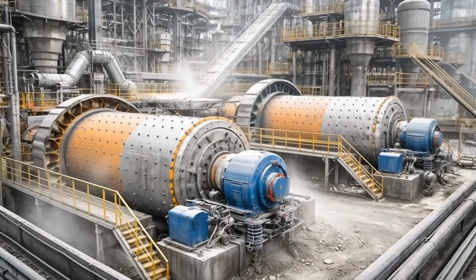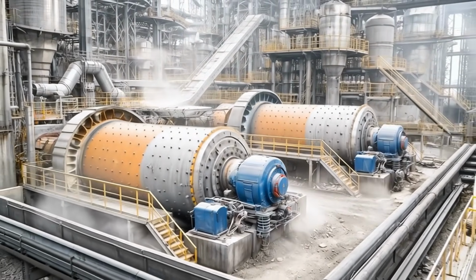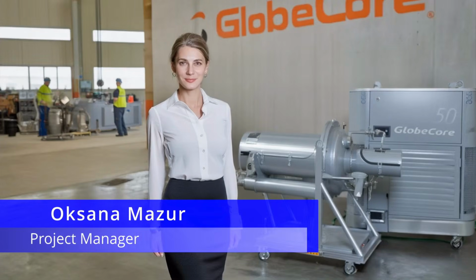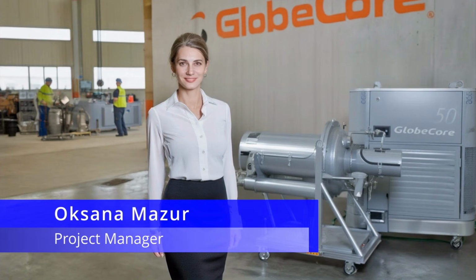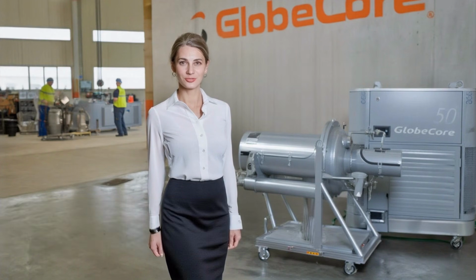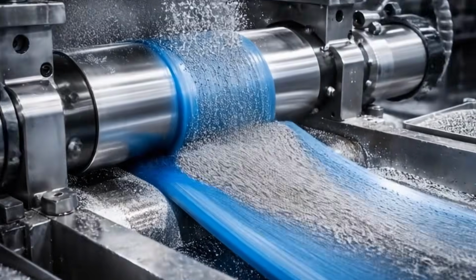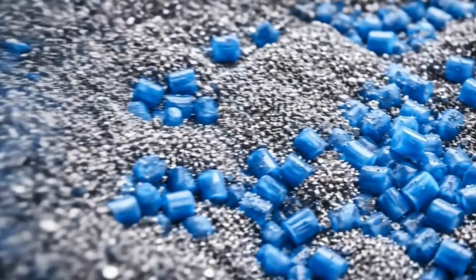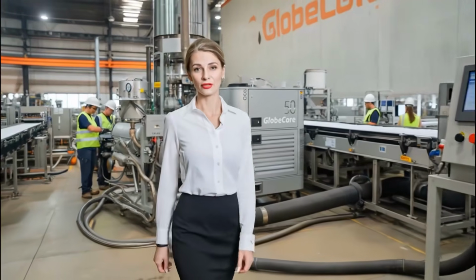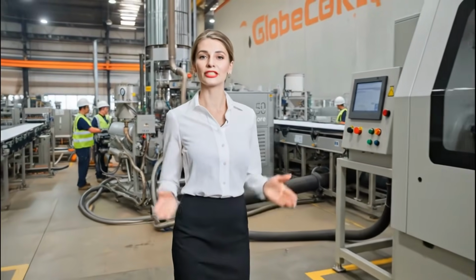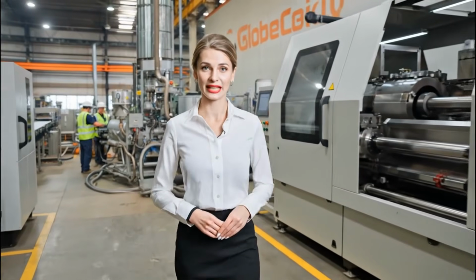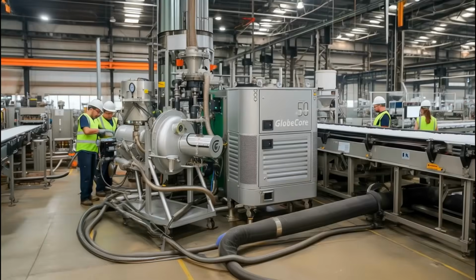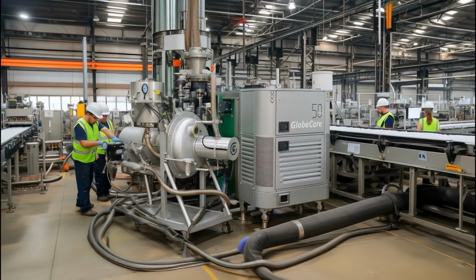That is why processing in AVSp produces an effect unattainable by conventional mechanical mills. In conventional mills, similar processes take tens of minutes or even hours. In AVSp, it takes just tens of seconds or even seconds. But the key difference is not just in speed. A ball mill forms a mechanical mixture where the components remain as separate phases. AVSp creates conditions in which the metal is fixed on the surface of the polymer particles. This makes it possible to achieve more stable electrical, tribological, and mechanical properties of the material without complex chemical modifications.